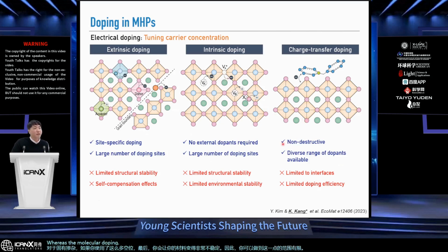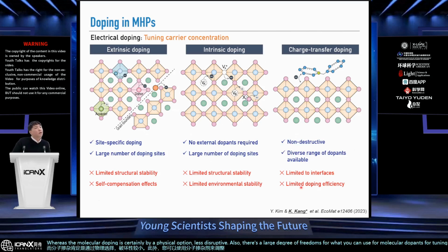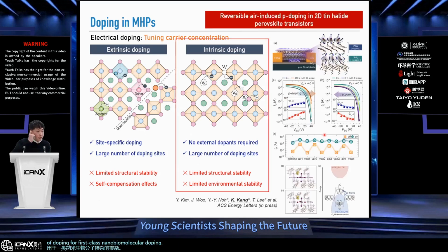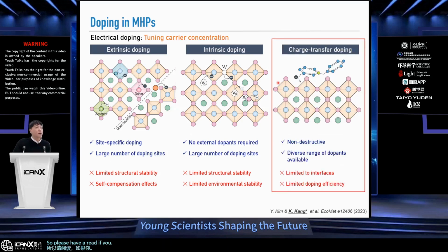Whereas molecular doping is certainly, via physical action, less destructive. Also, there's a large degree of freedom in what you can use for molecular dopants for tuning the energetics and also the interface properties. But this is mostly limited to the interfaces. So for example, here, like the interface. So it is a question of how to incorporate as many of these dopants as possible to have a high level of doping for perovskites via molecular doping. As a side note, I would like to tell you that we've recently worked on this intrinsic doping, and we've systematically and directly seen this effect of reversible air-induced p-type doping in perovskites, which has been recently published. So please have a read if you like.